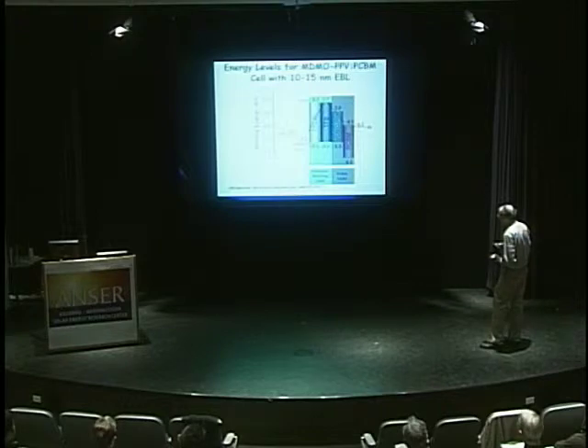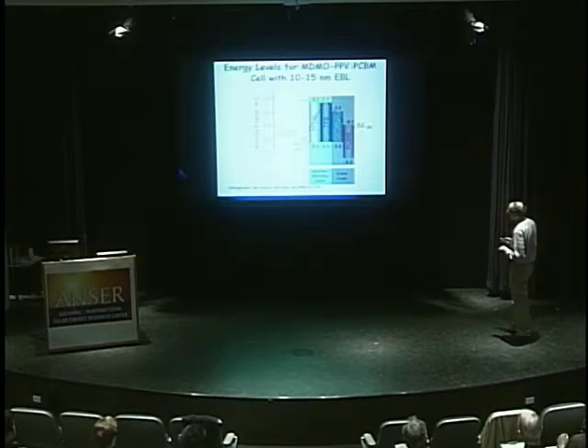And this is the material where we're going to completely do away with the PEDOT. So we're going to take this terrible stuff away, $100 for a little bottle of stuff that has a few milligrams of PEDOT inside, and we're going to do away with the PEDOT. And you see, and René showed already very nicely, when these plots start looking very, very square, that's a good sign. And so we get an efficiency of about 2.3%, so much better than our control with PEDOT, good fill factor, good short circuit current.